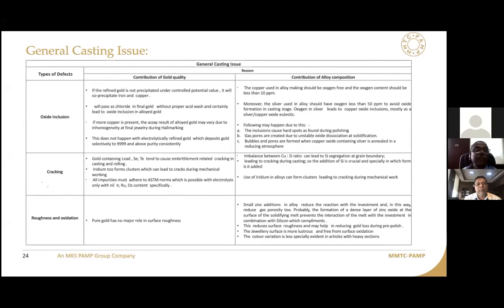and lead to more gold losses during polishing. The roughness: pure gold doesn't need much addition, but when you add zinc and silicon in a balanced way, the cast surface will be free from roughness. It will be smooth, it will be shiny, and with no oxidation effect. At the same time, you will get a uniform color all around the surface. So this is how the alloy can contribute.